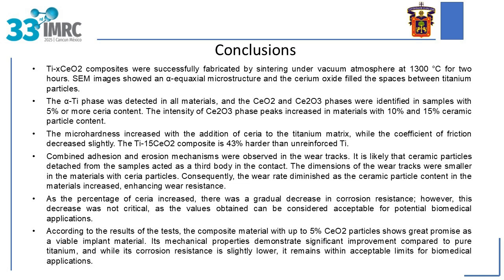According to the results of the test, the composite material with up to 5% ceria particles shows great promise as a viable implant material. Its mechanical properties demonstrate significant improvement compared to the pure titanium, and while its corrosion resistance is slightly lower, it remains within acceptable limits for biomedical applications.